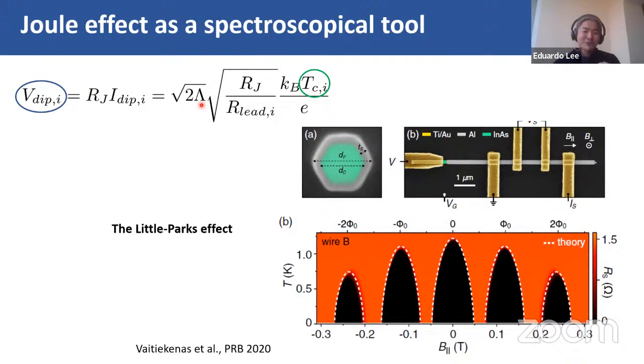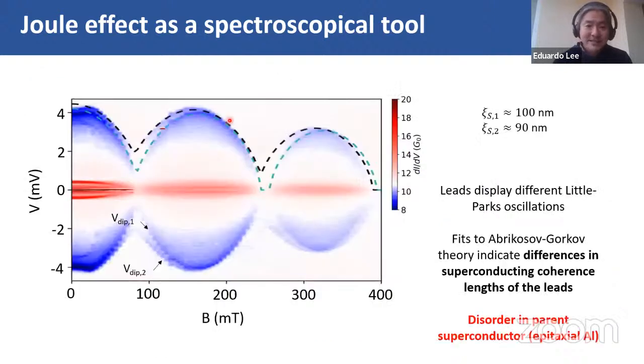So also with the Little-Parks effect, with the oscillations of Tc, this doesn't change so much. That's why our fits are not bad, I would say, throughout the measurement. Second question, about heat dissipation. For the model, we are neglecting electron-phonon coupling, assuming that all the heat is carried by quasi-particles in the leads. Is this a fair assumption? As I mentioned in the answer to Akash, we estimated how important electron-phonon coupling would be for dissipation, and we estimated it to be two orders of magnitude lower.